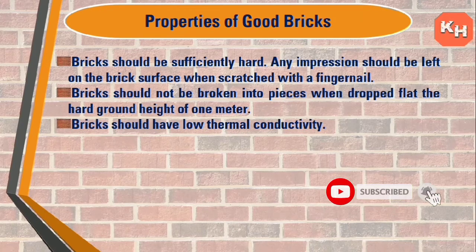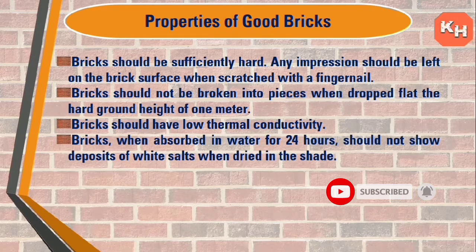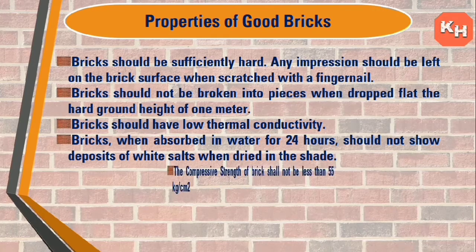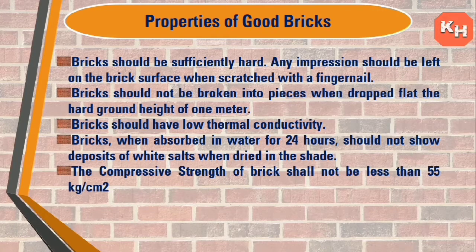Bricks should have low thermal conductivity. Bricks soaked in water for 24 hours should not show deposits of white salts when dried in the shade. The compressive strength of a brick shall not be less than 55 kg per cm².